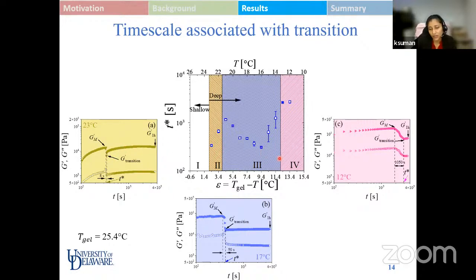In region 3, it is characterized by a sudden decrease, but not a very prominent increase in the modulus value, whereas in region 4, the drop is gradual and then followed by a plateau value. So the different meanings of these regions and what they are proposing will be coming up in the further slides.